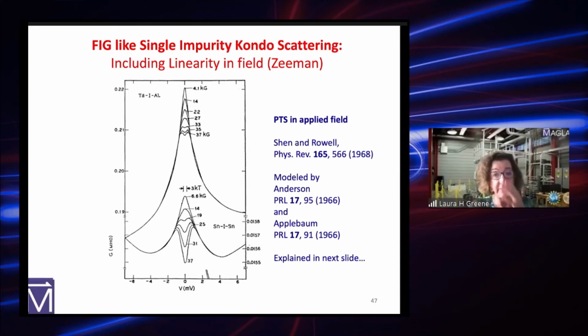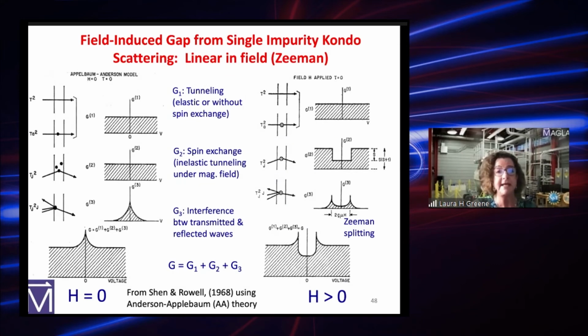Okay, so you're very familiar with this, Catherine, which is single impurity Kondo scattering. This was measured like crazy, and Shen and Rowell did this a long time ago. The way they described this was that there's some kind of magnetic impurity in the interface, either near or in the barrier in planar tunneling. As they applied a magnetic field, they saw the splitting. The explanation was given by Anderson and Appelbaum here.